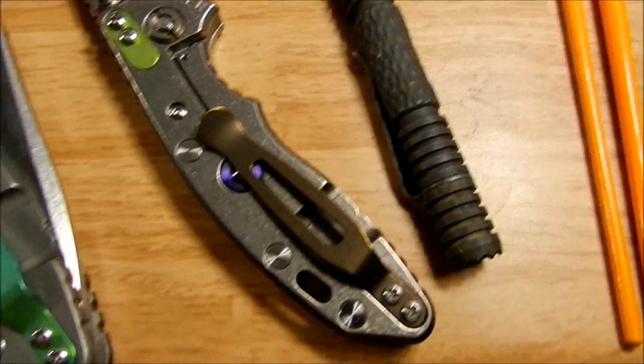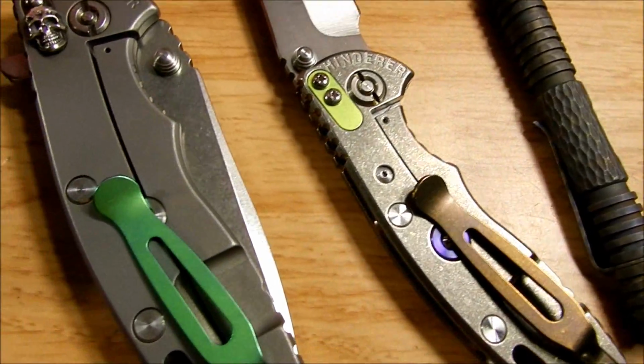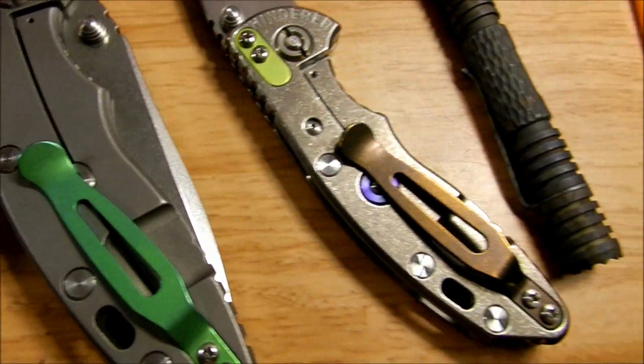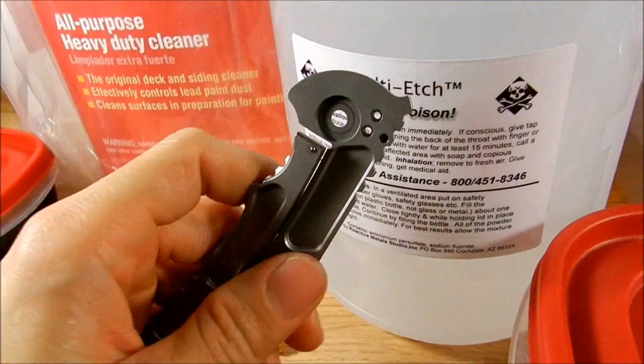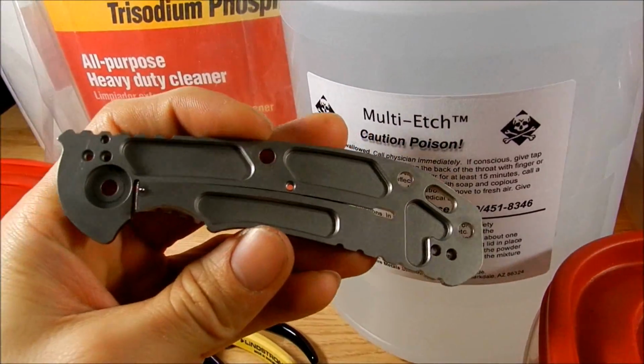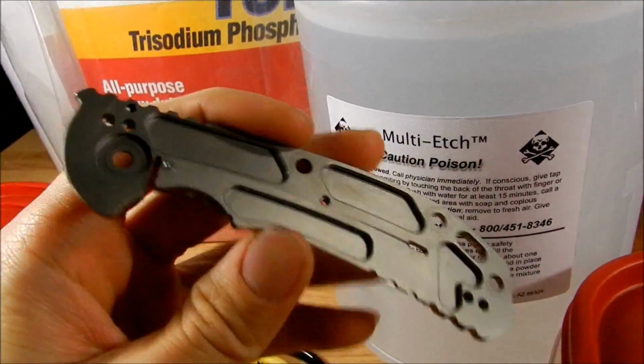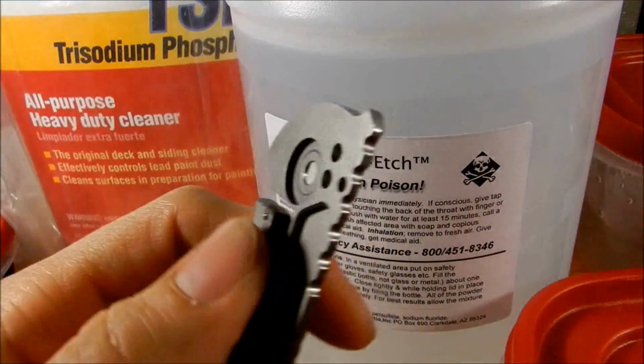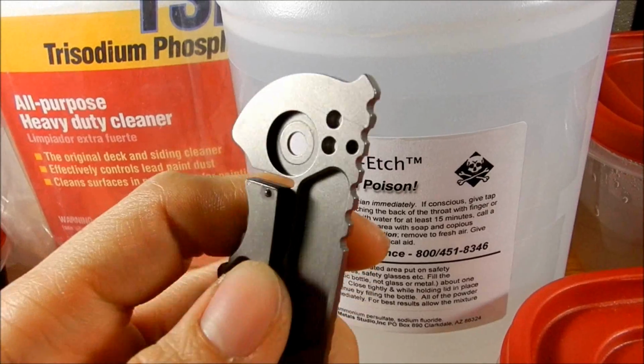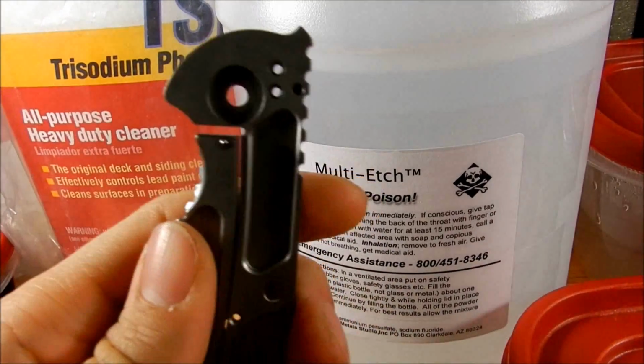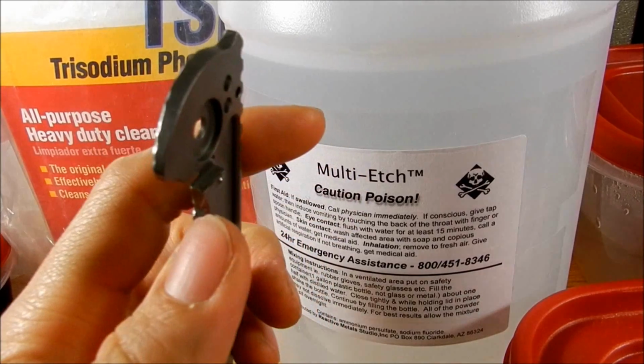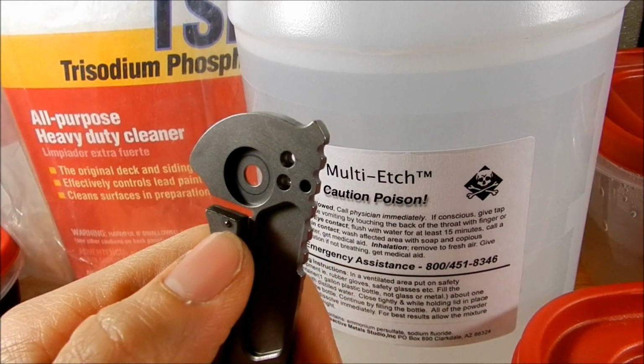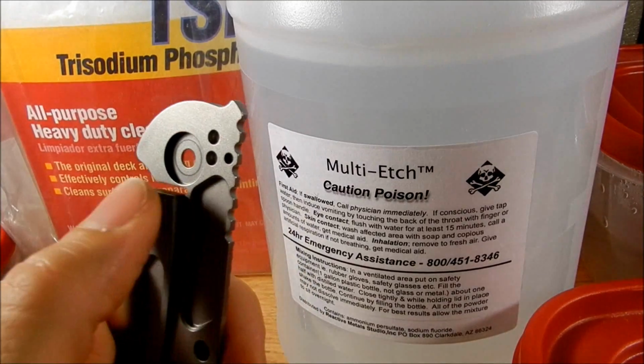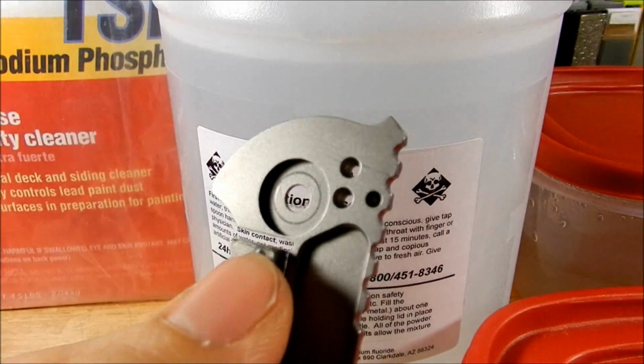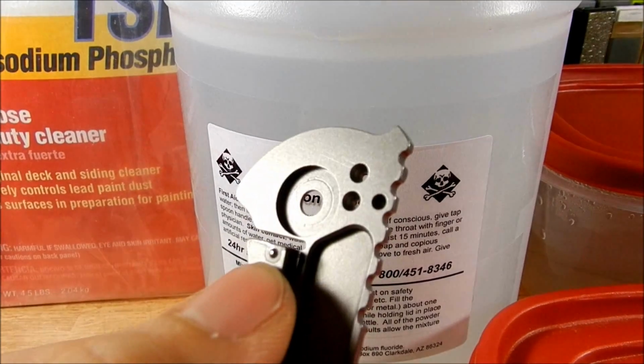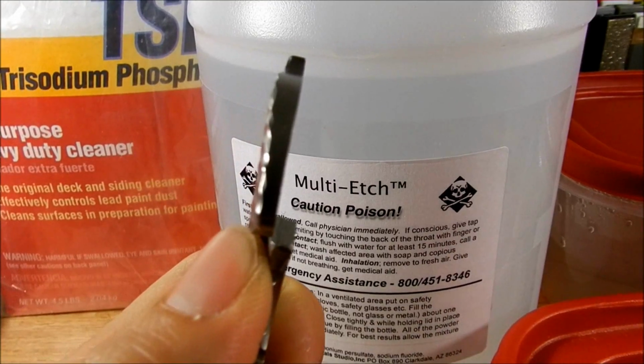So prep work is just as important as the other things if you want a real deep, consistent color on the pieces you're anodizing. When you're anodizing frame locks, like I said, nothing goes in your solution except titanium. With a frame lock, you have the detent ball, and you often have the lock face that is carbidized, and you do not want that in your etching solution. It will contaminate it, and when you're anodizing, it will actually draw away current from what you're anodizing. So what I do is put a thin layer of clear nail polish over the detent ball and over the lock face.